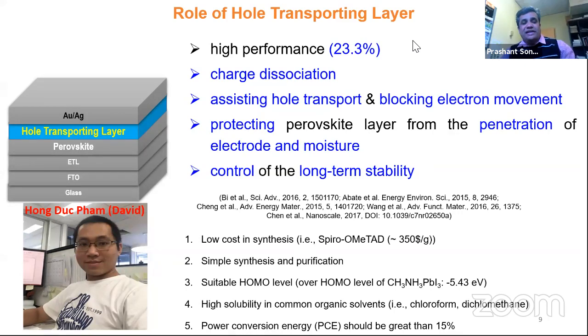The main principle while designing a low cost hole transporting material is that we should have a straightforward synthesis, which is very important. As you know, spiro-OMeTAD, which is commercially available and which most researchers use, is very expensive, $350 per gram, whereas the material which we wanted to synthesize should have a simple synthesis. It should have a simple purification and can be scaled up on a large scale. And importantly, its HOMO value should be close to the HOMO value of standard methylammonium lead iodide, which is 5.43 electron volt. But again, we can tune this HOMO value of the hole transporting layer depending on what type of perovskite layer you're using.